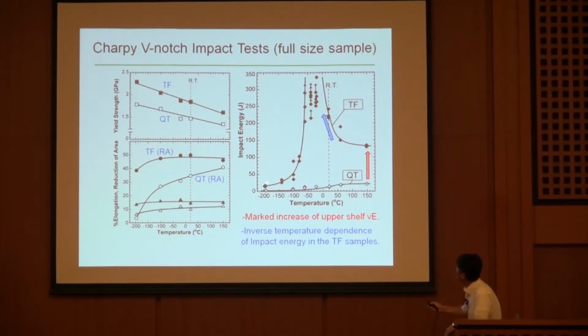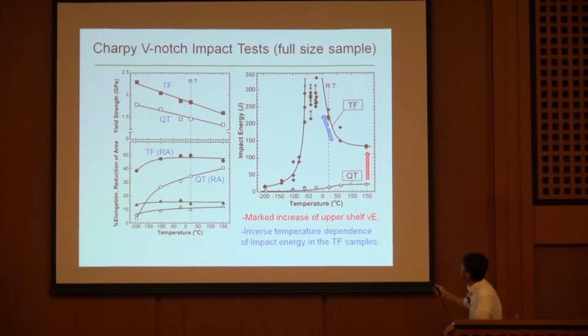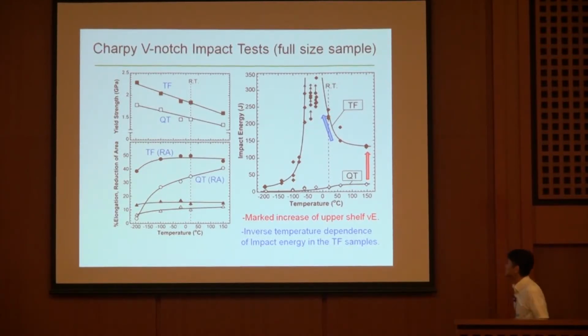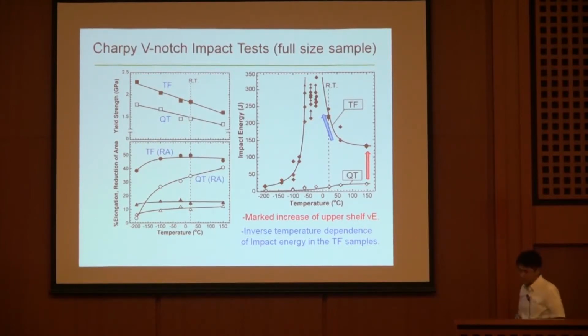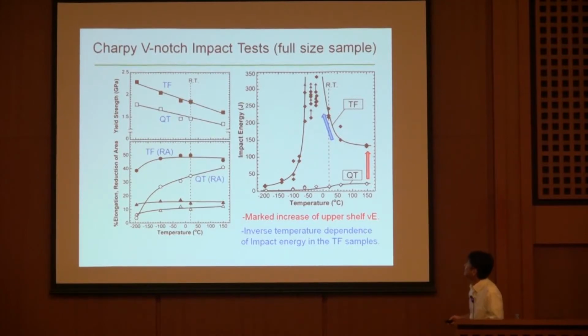As low as 20 or 30 joules. And the transition temperature range shows here. However, this absorbed energy jumped here, and an inverse tendency of impact energy is also obtained like this. At ambient temperature, you can see 250 joules. So a marked increase of upper shelf and inverse temperature dependence have been observed. We were so surprised when we looked at this data.